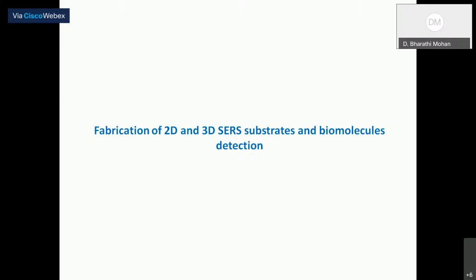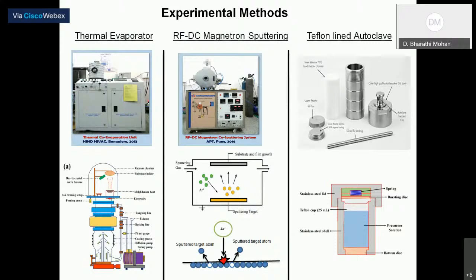Coming to the fabrication of 2D and 3D SERS substrates and the biomolecular detection. To fabricate the SERS substrate, we have a thermal evaporator, an RF DC magnetron sputtering system, and a Teflon lined autoclave. The thermal evaporator is used for the deposition of silver nanoparticles, whereas the RF and DC magnetron sputtering system is used for depositing the bimetal, and the Teflon lined autoclave is used for growing zinc oxide nanorods through hydrothermal reactions.